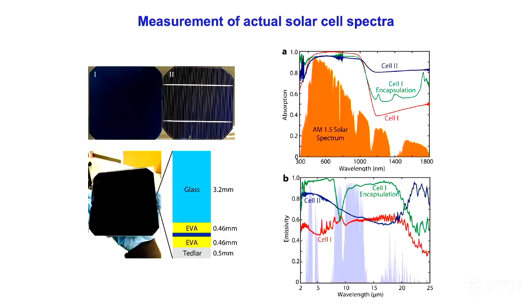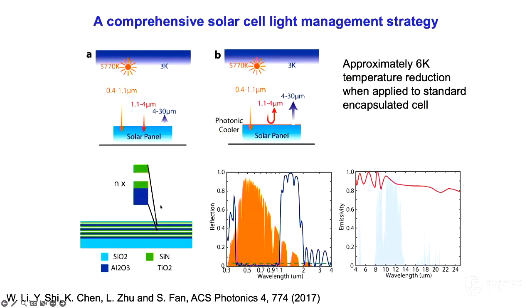the solar cell. So consequently, with Wei Li, we proposed this comprehensive solar cell light management strategy. We envision a coating that you can put on the solar cell that allows all the visible light to go through, but reflects the solar spectrum that cannot be used by the silicon cell, so that it won't use those spectrum to heat up the solar cell. And finally, we design it so that it's strongly emissive in the mid-infrared wavelength range for radiative cooling. The theory indicates that if you can do this, you will get a temperature reduction of about 6 degrees Celsius when applied to a standard encapsulated cell. And this translates to approximately 0.5 to 1 percentage point of solar cell efficiency improvement, which is quite substantial.